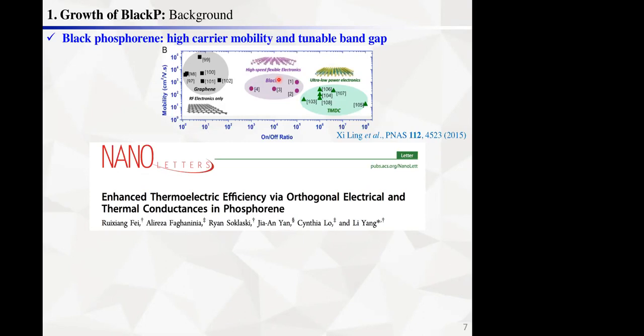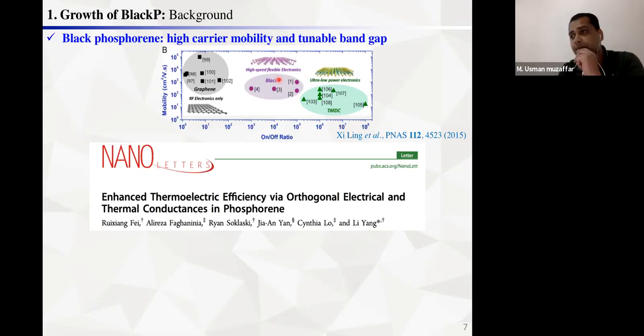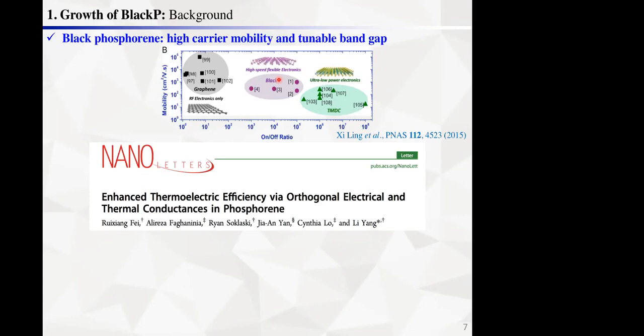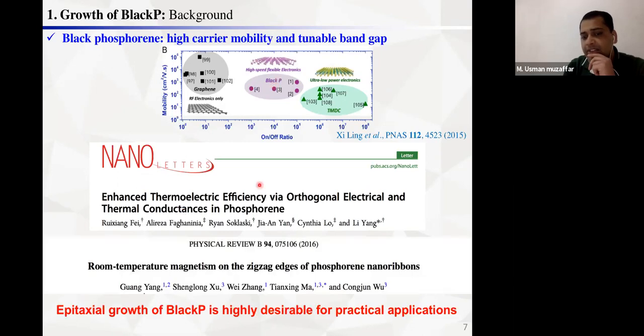And is there a way to control spin in this system, a spintronic system, in black phosphorus? In black phosphorene, yes, you can see this paper. Intrinsically, black phosphorene is not magnetic, but by constructing edges in the zigzag direction in nanoribbons, we can induce magnetism in this system.